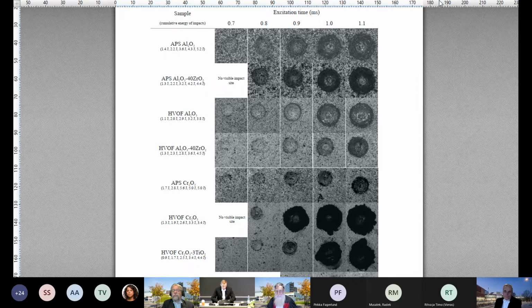To make it better for research use, I think it would be good for quality control of this type of damage tolerant behavior. If you always make the same coating with the same process and you know its behavior in the test, it would be really fast for this type of use. But for characterization, it would still need some instrumentation. I would want to say the velocity control and measurement of the impacting head would be key, and to be really able to control the energy, so possibly have a loop back where you input the energy you want and the machine does it for you and keeps the energy stable. But to start, it would just be repetitions of the same materials and trying out the limits of the machine a bit.